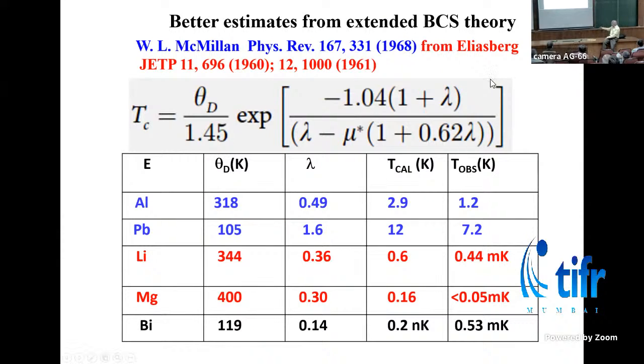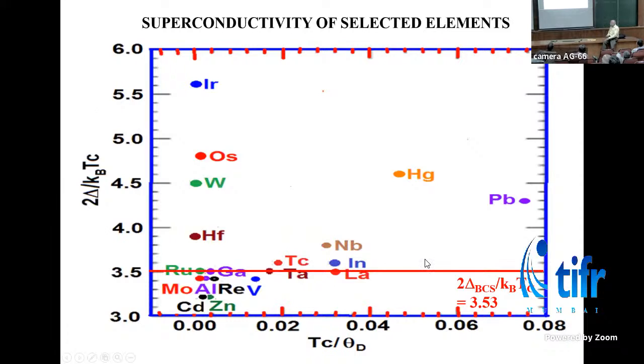And things like lithium, there I think there is a problem. Lead is very good. So is magnesium, there is a problem. Bismuth is even more a problem because theory predicts that it can never become a superconductor, whereas we see superconductivity at 0.5 millikelvin. So, and we move on.